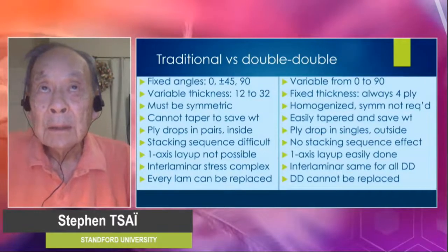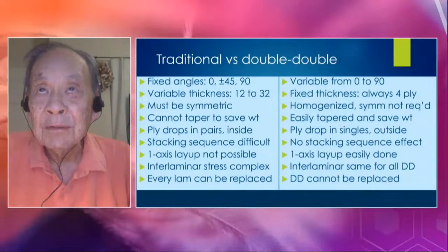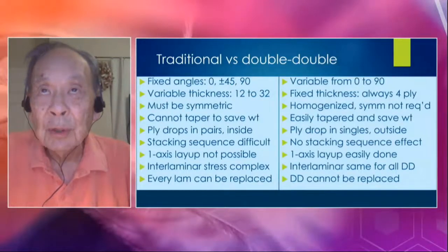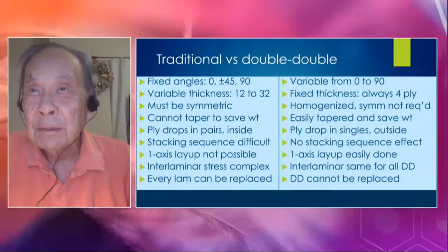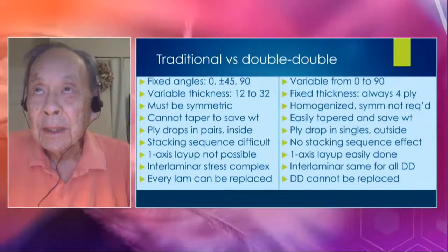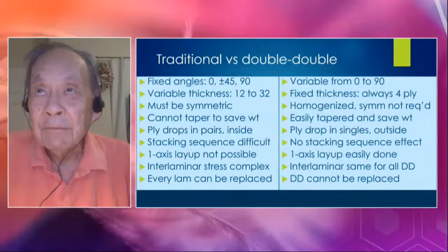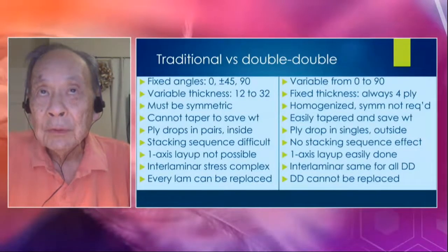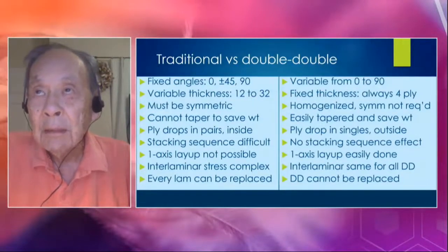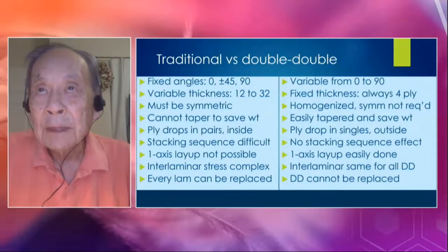Traditional on the left, where you have fixed angles, so 0, 90, plus or minus 45, but variable thickness from 12 to 32. Whereas double-double on the other side has variable angles from 0 to 90 and fixed thickness, always 4 plies, as Thierry just mentioned. So when you have only 4 plies, then you do not have to make the laminate symmetric, because you can homogenize the laminate by using a repeated number of stacks of the 4 plies. So that makes it very simple.